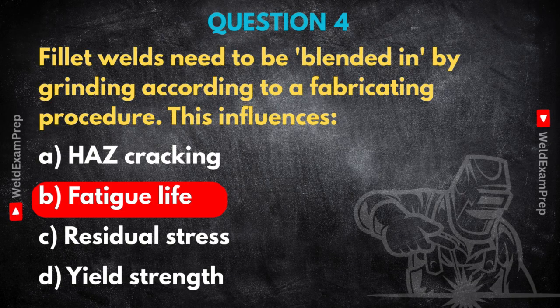Fatigue life. So grinding the weld isn't just making it look neat. Not at all, although a neat finish is often a side benefit. The crucial point is the toe of the fillet weld, that transition line where the weld meets the base plate. Geometrically, it's often quite a sharp transition. Yeah, but the little notch. Exactly. It acts like a notch, a stress concentrator. When the component is subjected to repeated loading and unloading, that's fatigue loading, stress gets magnified at that sharp toe. And that's where cracks like to start. That's precisely where fatigue cracks often initiate.